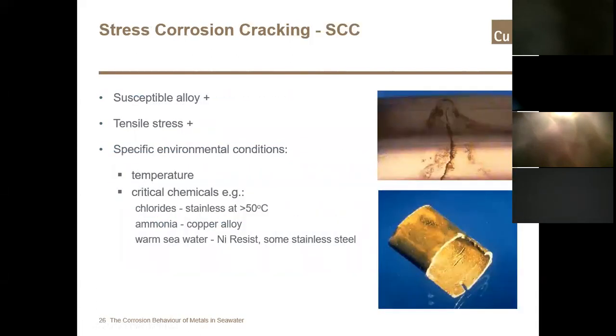The stress corrosion cracking is another issue that we've touched upon but not really gone into any depth on. Now, for stress corrosion cracking to occur, you need to have a susceptible alloy and a combination of a tensile stress and corrosive environment. So, for example, steels can stress corrosion crack in the presence of chloride at greater than 50 degrees C, or in the case of copper-based alloys, in the presence of ammonia. Failures due to stress corrosion cracking can be very unpredictable, and virtually all alloy systems can be susceptible under specific conditions. So it is something to be aware of and something to look at.